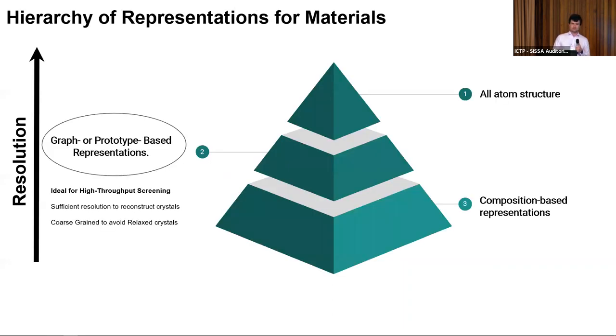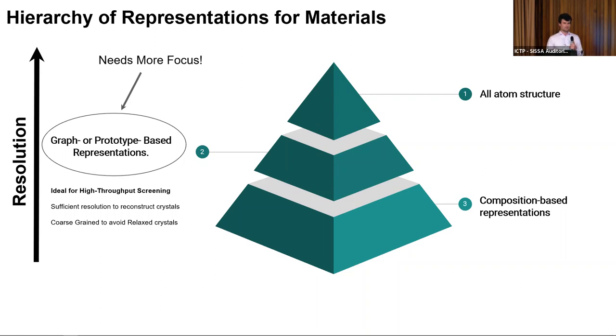What you would need for this kind of task is some kind of graph or prototype-based representation with sufficient resolution to reconstruct the crystal structure from the representation itself, while being coarse-grained enough to have the same representation for both unrelaxed and relaxed crystal structures. However, there are barely any representations for materials in this class, so this area needs a lot more focus.